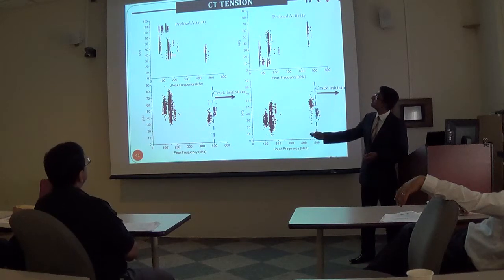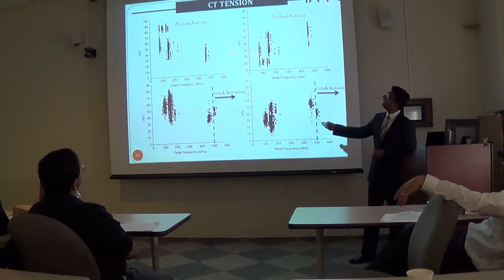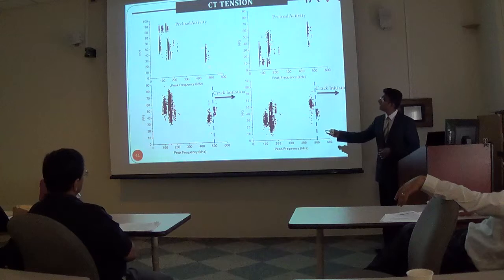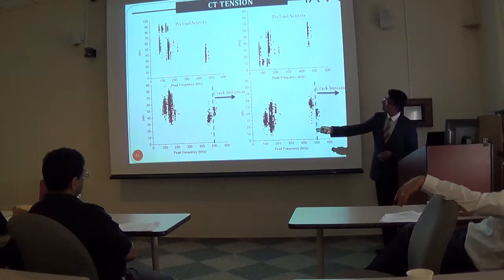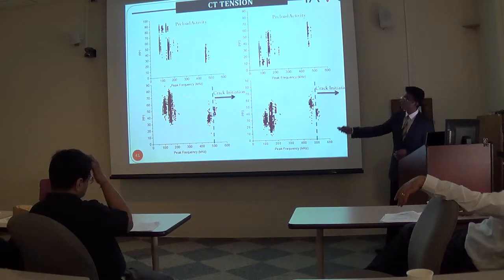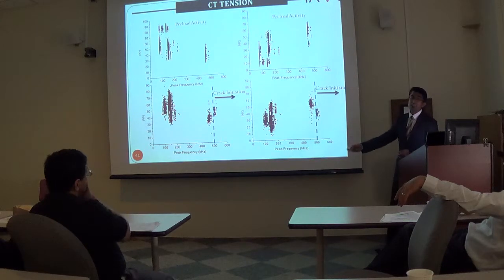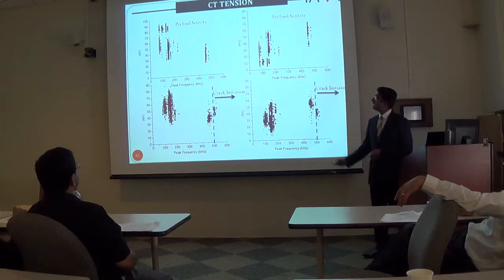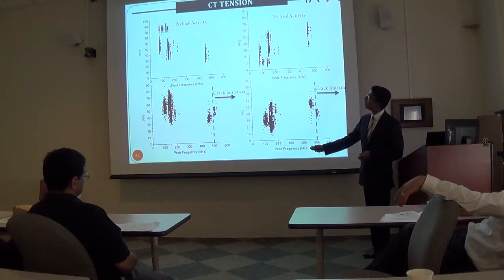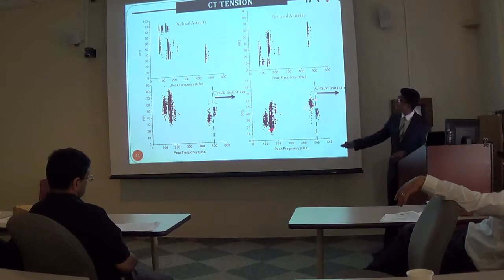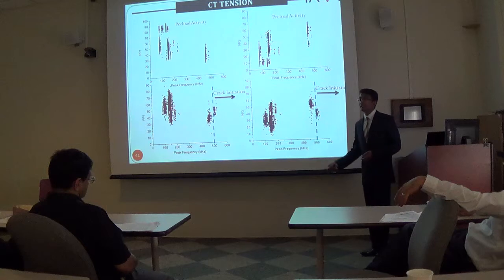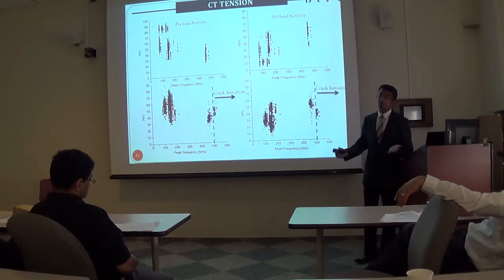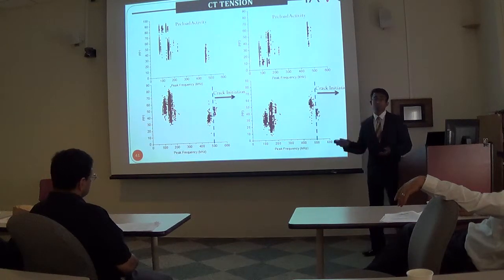material. And you can see that the partial power analysis performed with the AE signals that were collected during the preload activity were seen to be much less than 500 kilohertz, as you can see here. But upon the crack initiation, you can see the activation of 500 kilohertz. Additionally, you can see the drop of the partial power 1s after the crack initiation, while you can see the partial power 3 signals increasing. This clearly indicates a shift from low frequencies to high frequencies that were generated due to the crack initiation in